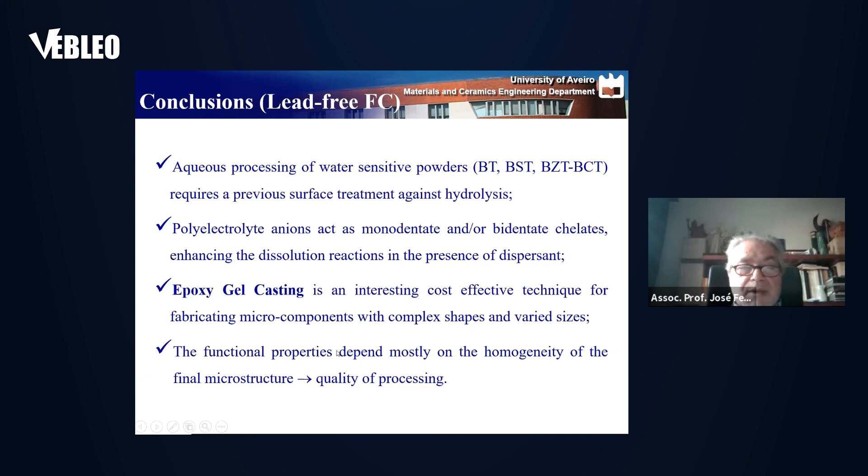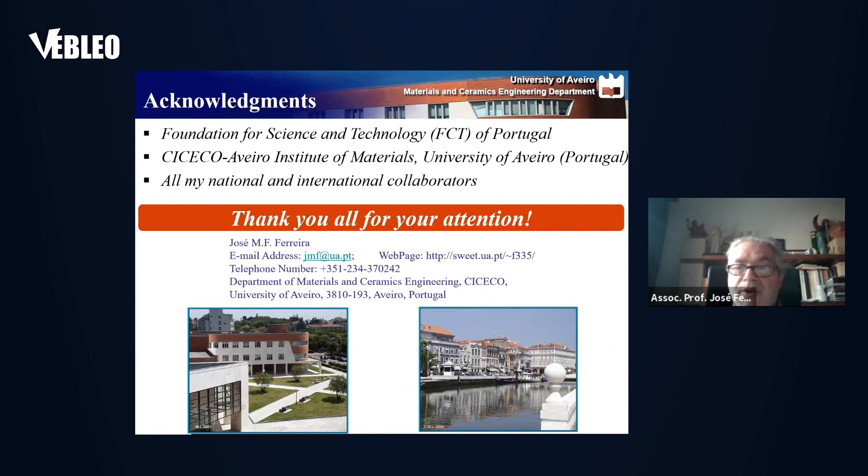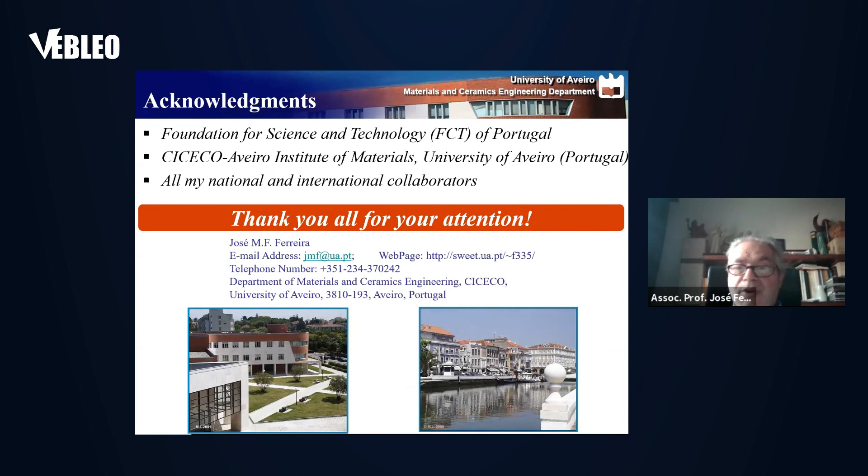To conclude: aqueous processing of water-sensitive powders like barium titanate, barium strontium titanate, and BZT-BCT compositions requires a previous surface treatment against hydrolysis. Polyelectrolyte anions act as monodentate or bidentate ligands and enhance dissolution. Epoxy gel casting is an interesting, cost-effective technique for fabricating micro-components with complex shapes, and the functional properties depend mostly on the homogeneity and quality of the final microstructure. Thank you for your attention.